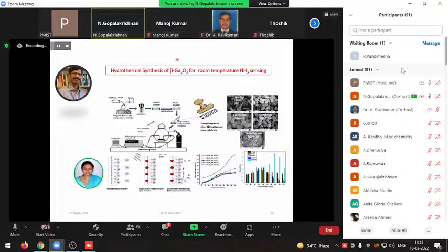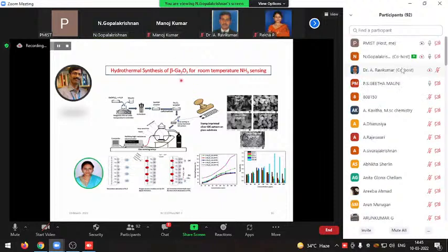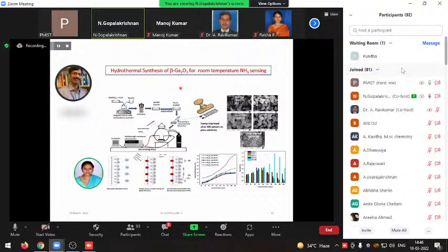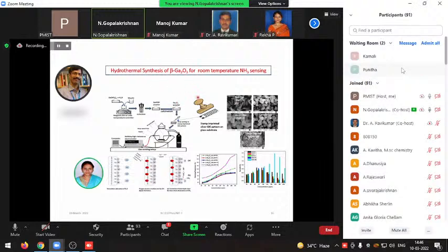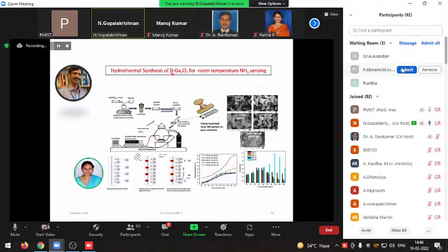That is very advantageous. It means it has a breakdown voltage almost 20 times higher than that of silicon, or 3 times higher than that of gallium nitride and silicon carbide. So it has a high breakdown voltage. Also, its figure of merit is about 3,000 times higher than silicon, 4 times higher than gallium nitride, and 10 times higher than silicon carbide. So it has a lot of advantages. In the future it may replace almost all high power electronics devices. Beta gallium oxide, please note that.